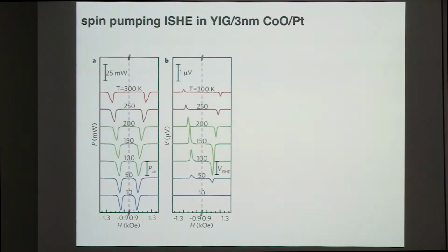And we can do the temperature sweep in our PPMS system. You can see that the absorption does not vary much, but it does have some temperature dependence. But if you look at the temperature dependence of the inverse spin Hall effect, obviously it's not monotonic. You have a very small value at room temperature. If you go down, it suddenly becomes big, and if you go down further, it turns small, and finally it vanishes at 10 Kelvin.